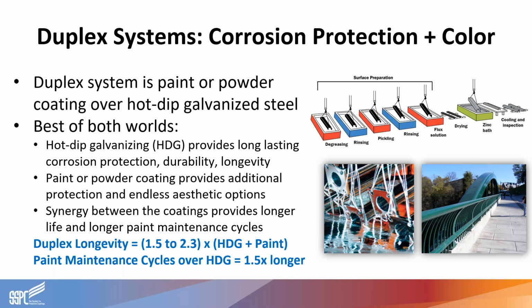So this is where steel parts are sent after fabrication, and then these assemblies are going to be immersed in a series of pre-treatment tanks to chemically clean the steel. Then those same parts will be placed in a kettle of hot molten zinc, and that will form the galvanized coating by metallurgical reaction. Hot dip galvanizing provides long-lasting corrosion protection in atmospheric environments, and it provides a very durable and long-lasting coating. Meanwhile, the paint or the powder coating will provide additional corrosion protection and also allows color to be added into this overall system.